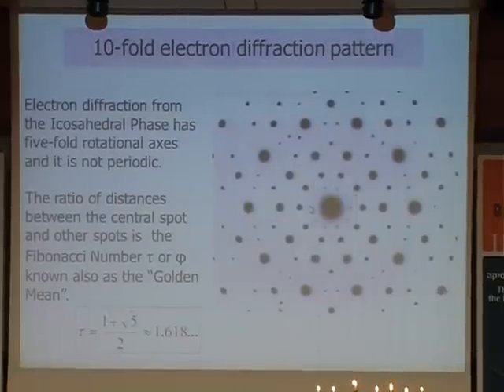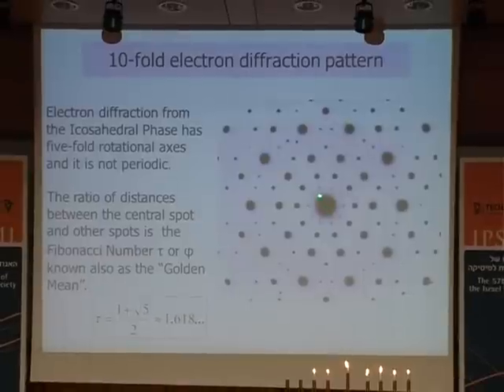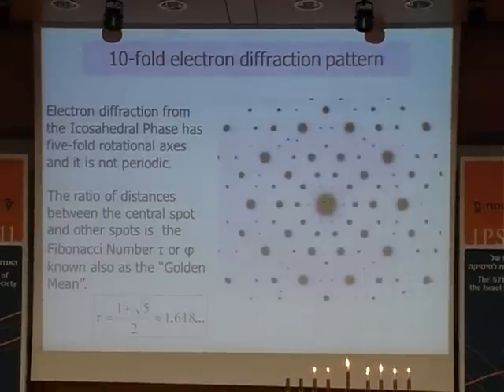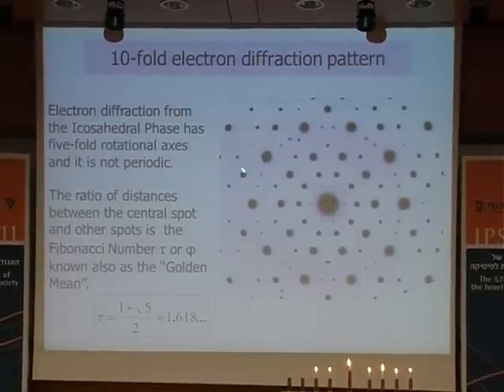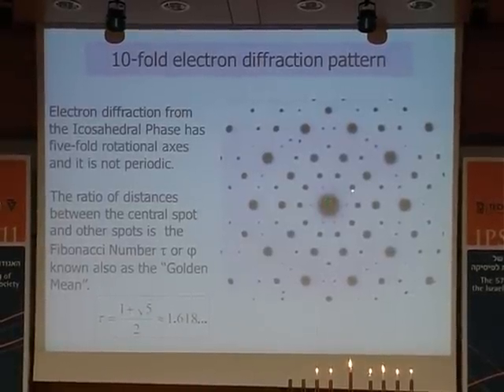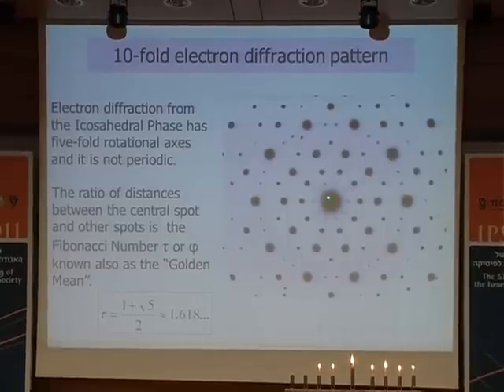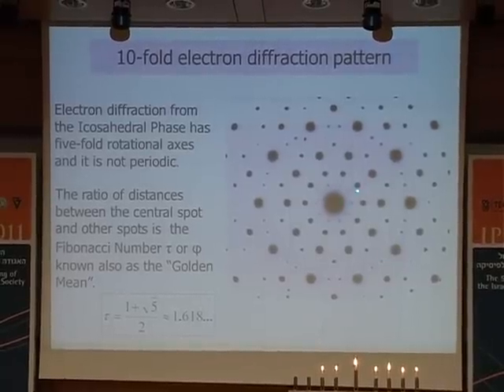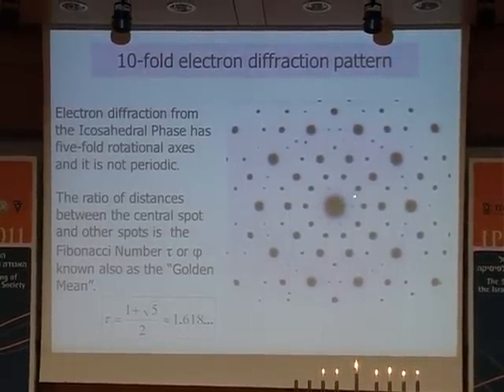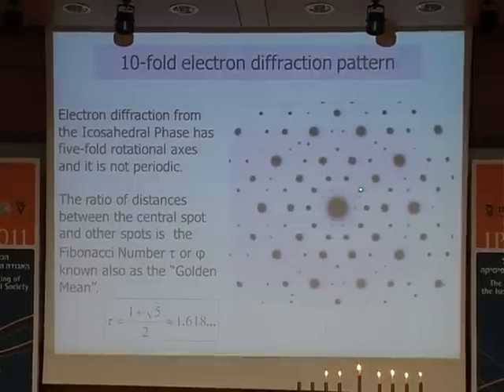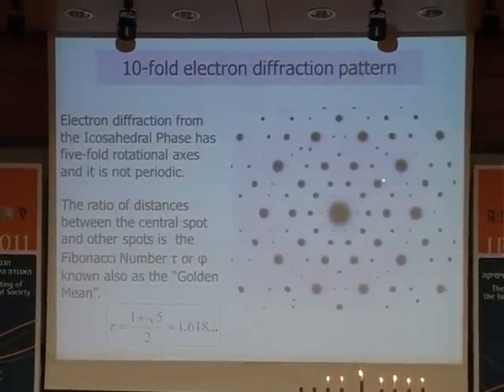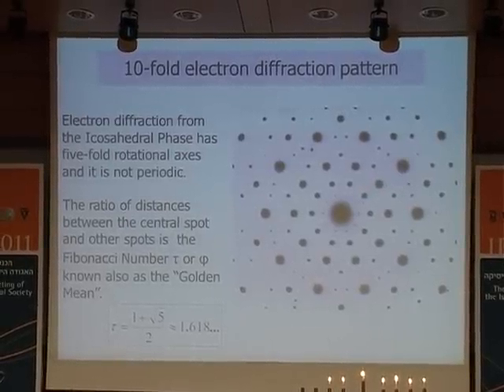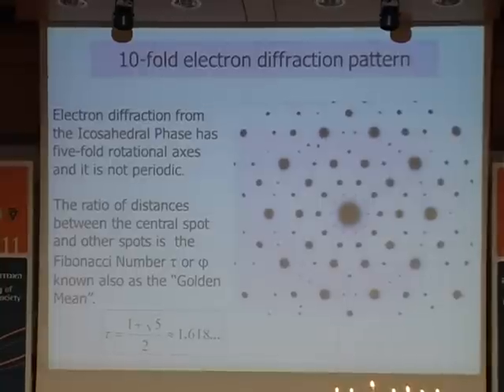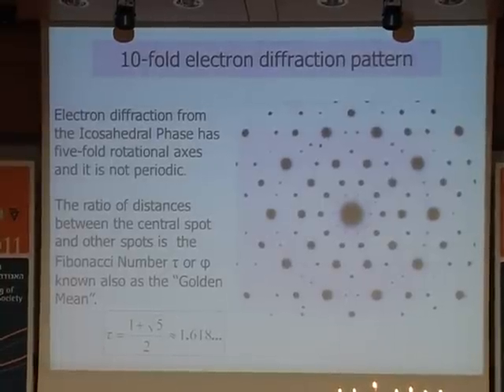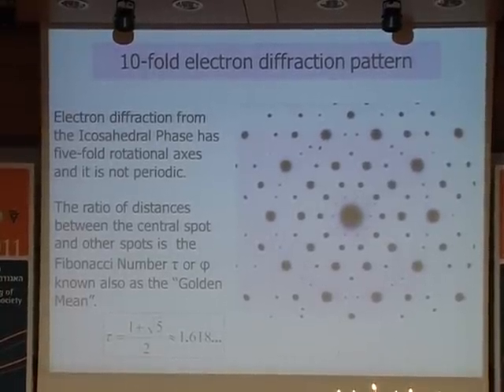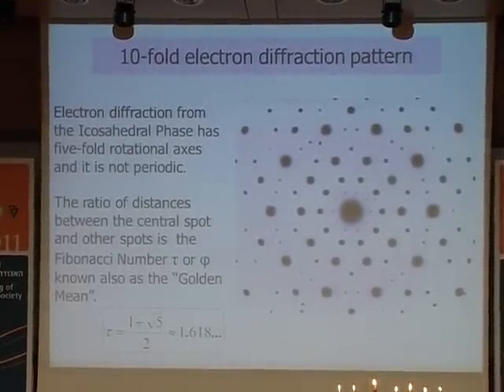Moreover, if you go back for a second and look at this diffraction pattern, if you look for the periodicity, it's not there. If you go along one line and you take any distance, say from the center to this spot, and you multiply it by an integer, say 2, you arrive here, and there is no spot there. So there is no periodicity. Tenfold, no twins, no periodicity. That's interesting.